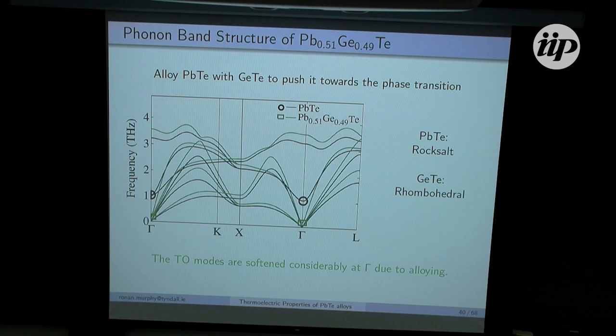So to demonstrate that, I have here again phonon band structures. Lead telluride is in black, and in green, I have this lead 51 germanium 49 telluride alloy. Now I've chosen this specific composition, again, as is the case for strained lead telluride, to push the alloy to the verge of the phase transition, but keep it in the rock salt phase.